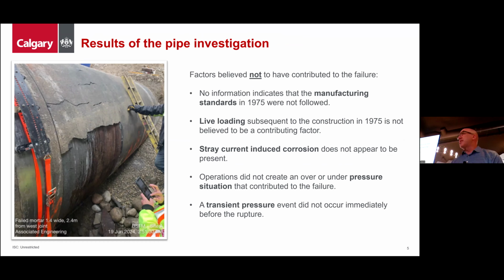Some of the things that did not contribute to the failure, first off, is there's no information indicating that the manufacturing standards applicable in 1975 were not followed. I know that some of our counsel were trying to attest that we had substandard materials in 1975. Some of them went so far as to say that the pipe manufactured in Quebec was susceptible to lower quality steel because of steel issues in Montreal and Quebec at the time, and that is definitely not the case. We had followed all of the necessary testing and all of the construction standards of the time as well.